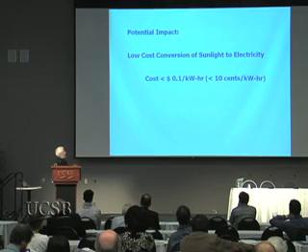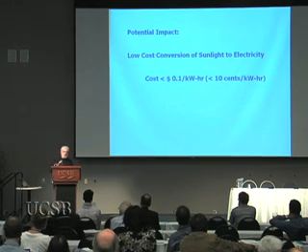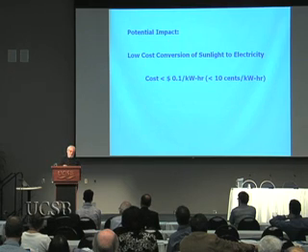So this number, which is, by the way, obviously a very attractive number, would be approximately the right number if we had devices with 8% efficiency and a lifetime of 8 years. Okay? We're going to be able to do that. I'm really confident of that. We have in our labs today a 6% efficiency, and there have been experiments at Konarka which have already shown that one can get to several years of lifetime. So I'm pretty optimistic that we can do that.